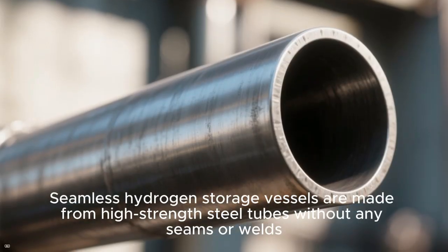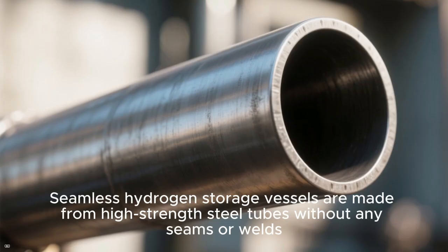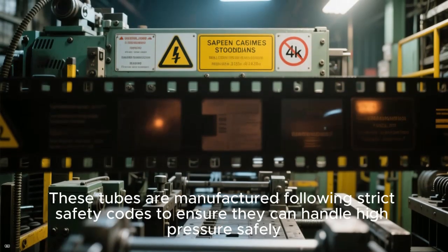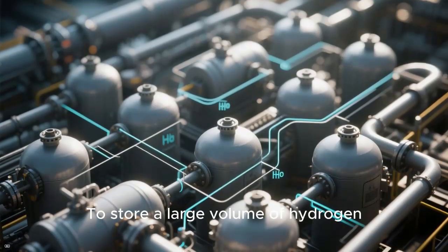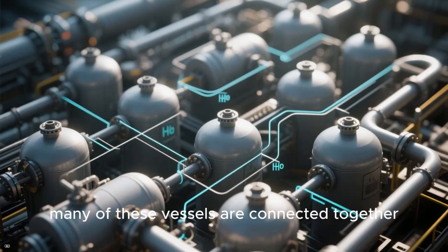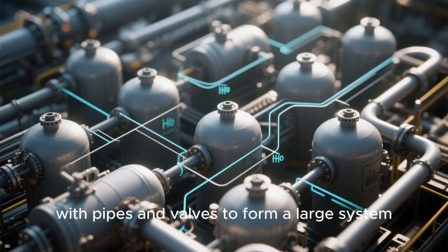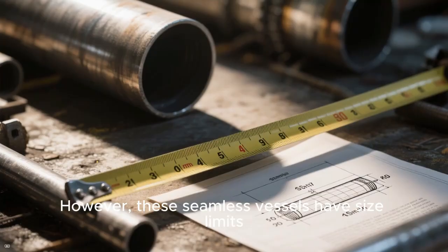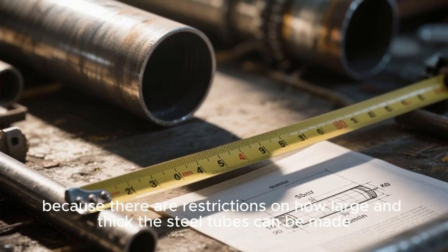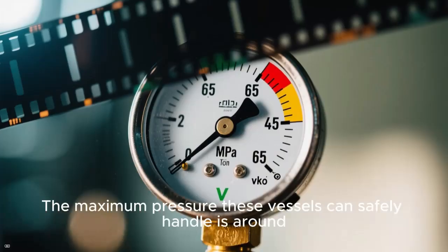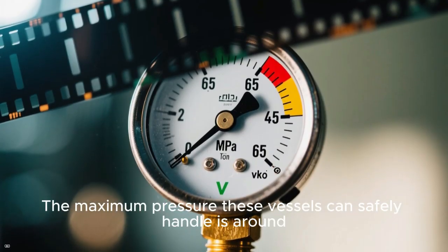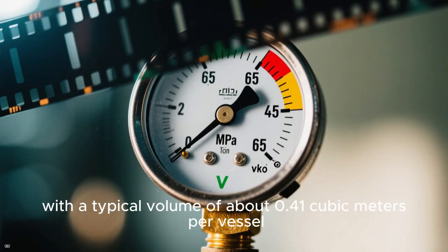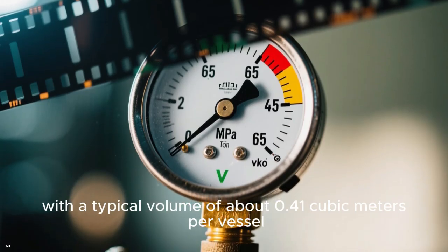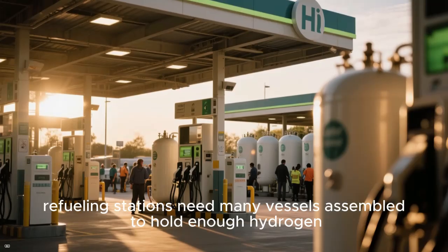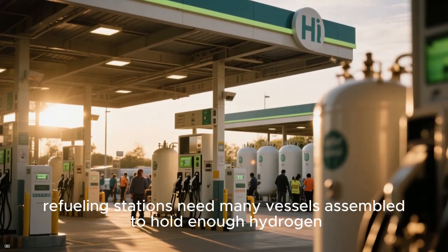Seamless hydrogen storage vessels are made from high-strength steel tubes without any seams or welds. These tubes are manufactured following strict safety codes to ensure they can handle high pressure safely. To store a large volume of hydrogen, many of these vessels are connected together with pipes and valves to form a large system. However, these seamless vessels have size limits because there are restrictions on how large and thick the steel tubes can be made. The maximum pressure these vessels can safely handle is around 65 megapascals (MPa), with a typical volume of about 0.41 cubic meters per vessel. Because of these limits, refueling stations need many vessels assembled to hold enough hydrogen.